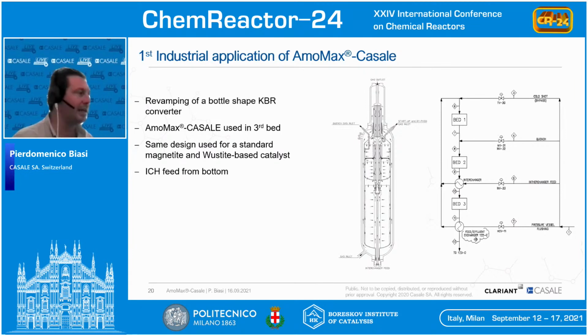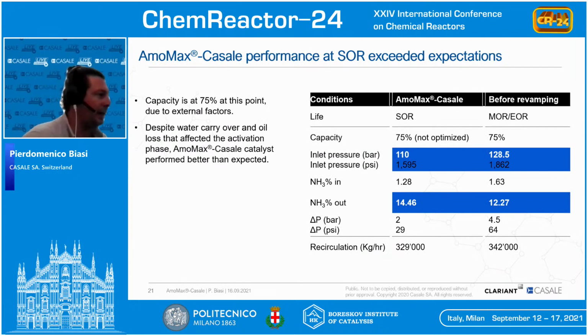We made this case, the client accepted, and then we loaded the reactor in 2020. So what we observe is that we make the new reactor and the catalyst, we make the revamping, and we compare the performances before and after the revamping. What was really important is that we were able to reduce the inlet pressure of the synthesis loop by almost 20 bar, and also to increase the outlet ammonia concentration by 2% absolute, that went from 12 to 14.